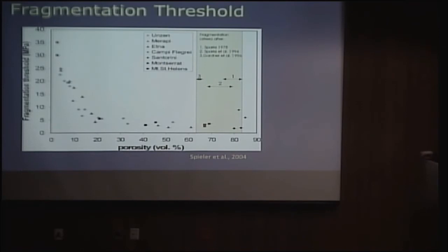So what we see here is a kind of a dynamic tensile strength which varies from about 30 to about 3 megapascals depending upon the bubble content. So if you have a system with variable bubble content, which you generally do in magmatic systems, you know that this material is going to fail earlier and much more efficiently than this material. And that's the reason that the biggest eruptions are dominated by bubble-rich materials. They're the weakest materials and they go first.